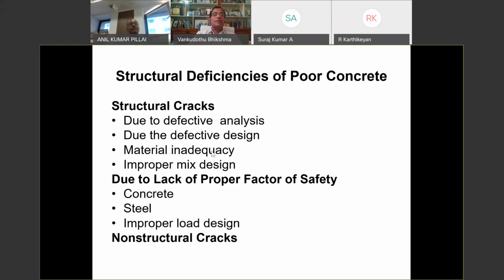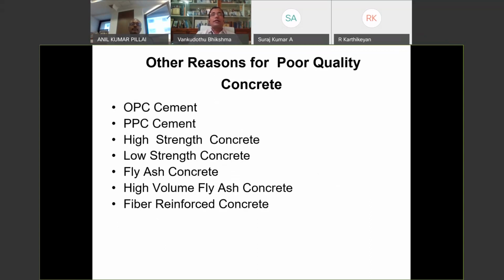Due to defective analysis, defective design, defective material, improper mix design, there are several reasons for cracks actually. Due to lack of proper factor of safety, which sometimes is not maintained properly, cracks may also come. Other reasons for poor quality concrete may be OPC cement, maybe PPC cement. Why will cracks come with OPC cement? Because OPC cement has high heat of hydration. High heat of hydration leads to cracks.